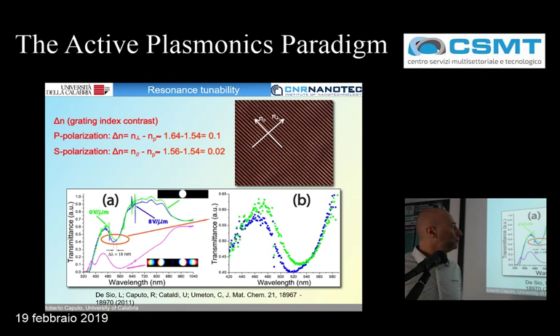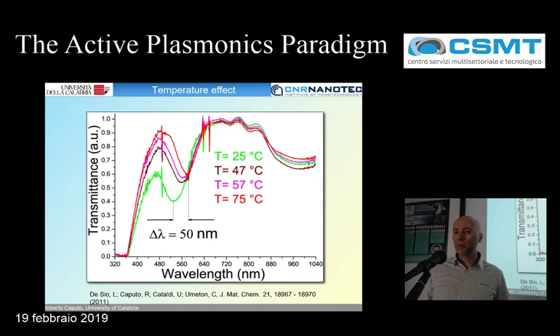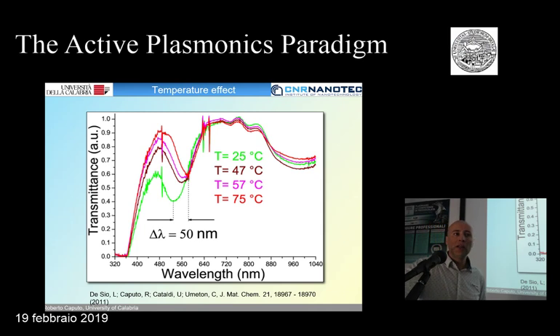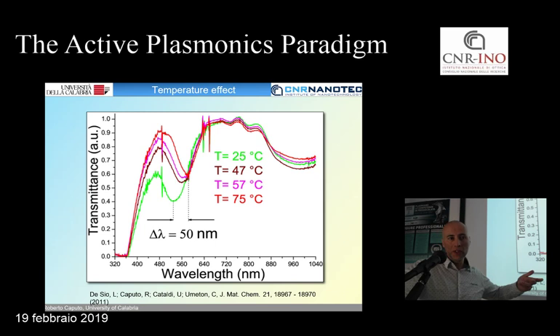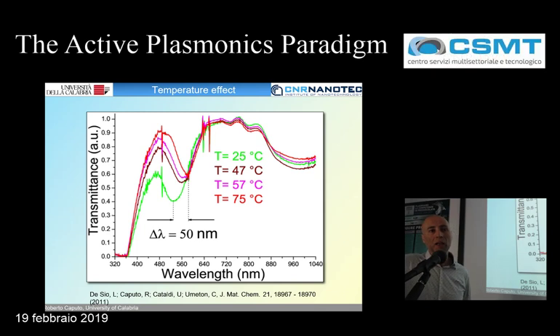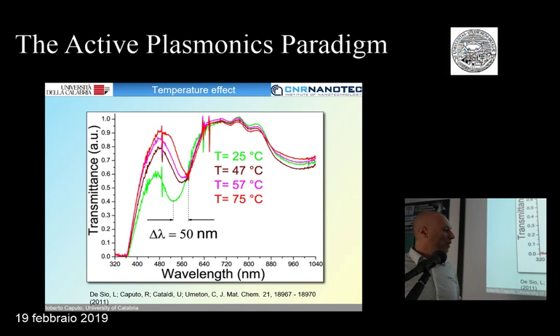And it's also reversible. When you change the temperature of the system, the shift is more remarkable, about 50 nanometers, because the liquid crystal tends to go to the isotropic phase. So it starts from a cholesteric phase. By increasing the temperature, it loses order and changes its refractive index, and in practice, you modify the surrounding medium again to get this very nice shift. So this was the preliminary result obtained in 2011, and we started working in that direction also with another approach.